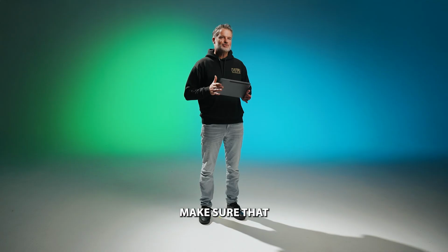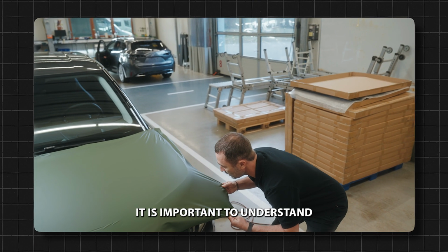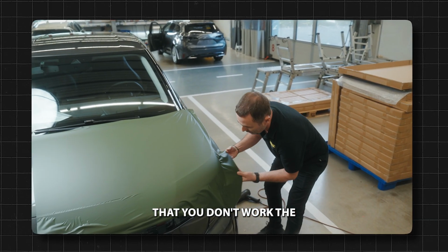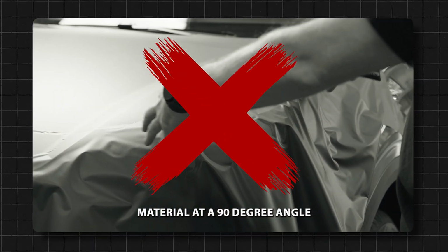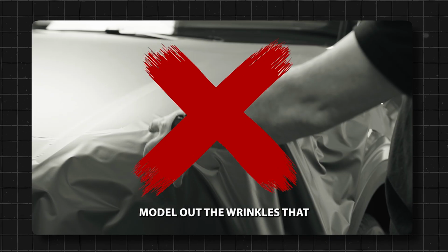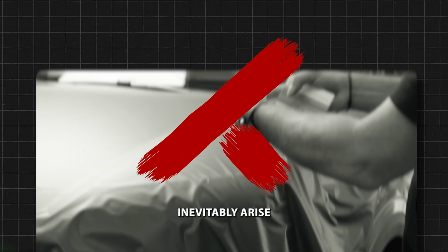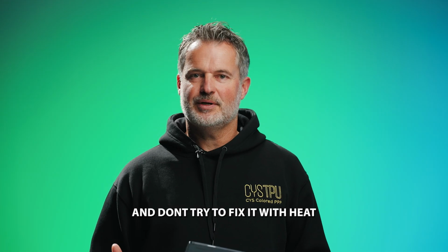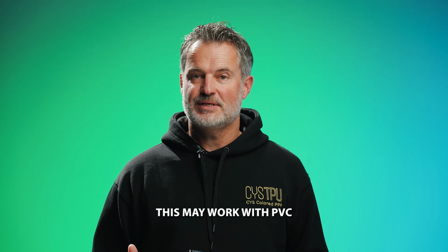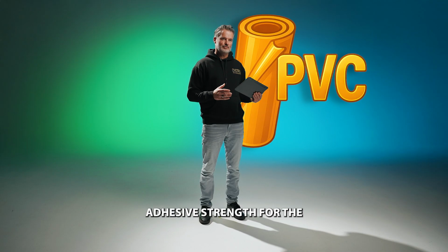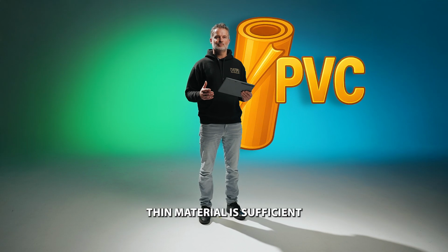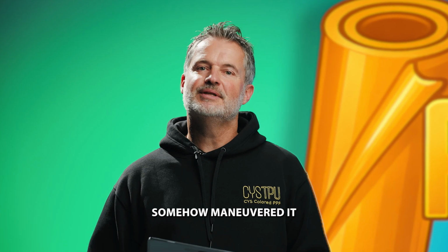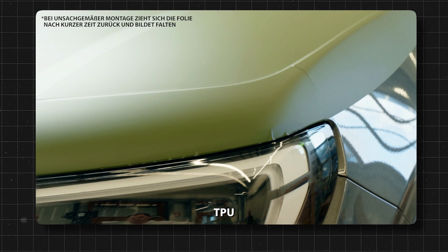The tension-free installation of TPU is very important. Make sure that you only stress the material as little as possible. It is important to understand that you don't work the material at a 90-degree angle up to a corner in order to then model out the wrinkles that inevitably arise, and try to fix it with heat. This may work with PVC. PVC forgives it because the adhesive strength for the relatively thin material is sufficient to hold the foil where you somehow maneuvered it. This mistake, which is made with PVC, takes its toll on TPU.